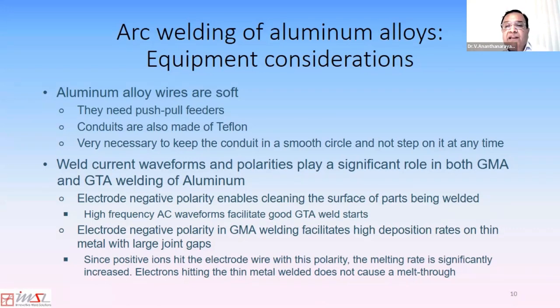And the negative polarity used, say, when you're doing alternating current waveforms in welding aluminum, helps the cleaning of the surface of parts. Because when the polarity is negative, it's the electrons that hit the metal, and they tend to clean up the surface prior to the welding. And also the negative polarity makes the positive ions hit your electrode wire, so you get very high deposition rates as well.